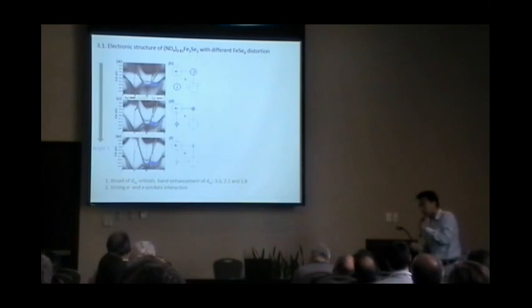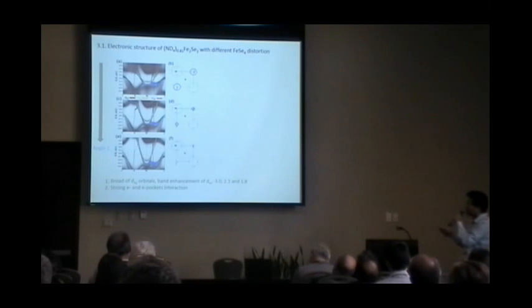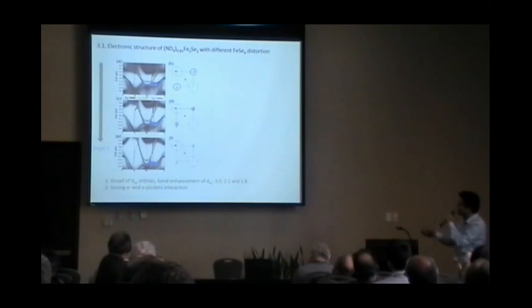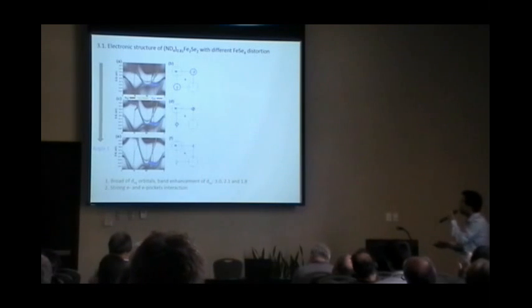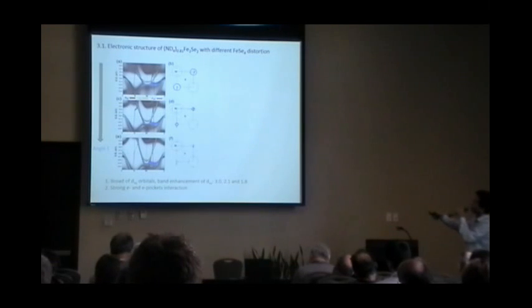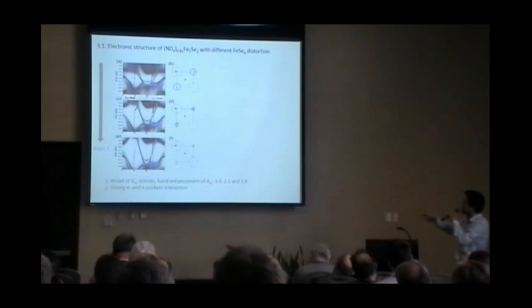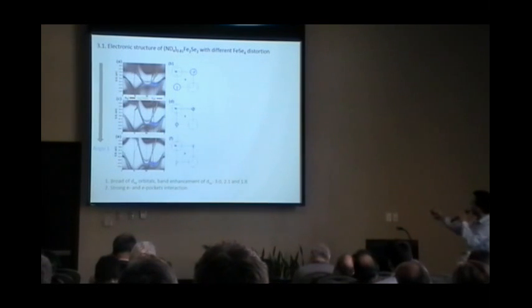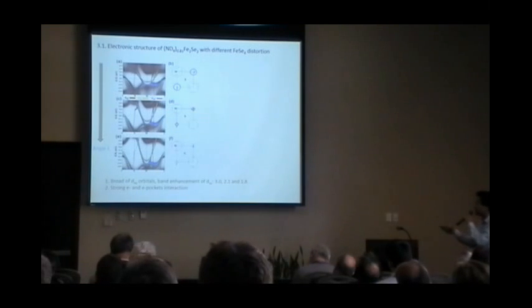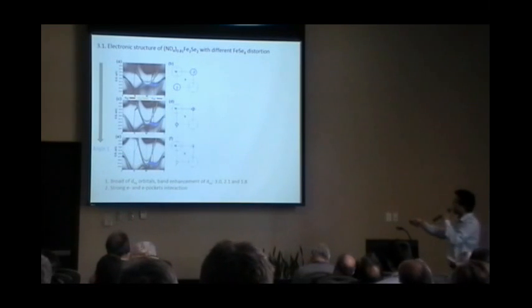So after we got this trend, we want to know why. So here we co-worked with some theoretical guys. We got this band structure. We also got the Fermi surface. From A to E, we increase the angle. So we can see two features shown here about the band structure. One feature is that from A to E, the band is more broad. It means the band's enhancement is very small in the E case.